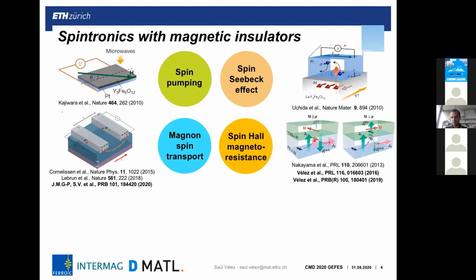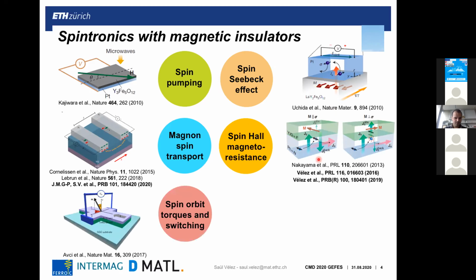And this leads to magnetotransport effects that allow us to read the surface magnetization of magnetic insulators. It has also been shown that you can exert torques on the magnetic insulator, and for large driving currents, you can even switch the magnetization of this magnetic layer. So you can manipulate the magnetization.